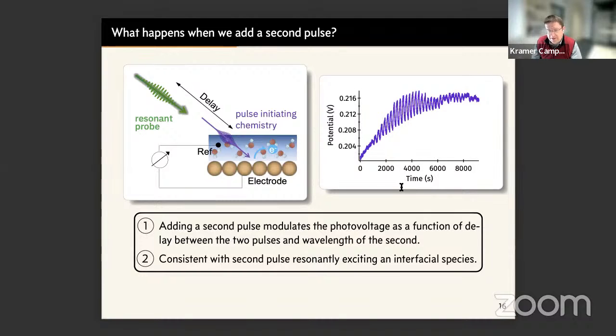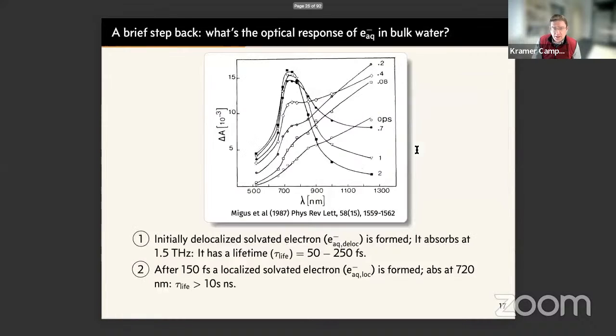So once again, this is just the seconds right off the potentiostat. And each of these spikes correspond to a different delay between this UV pulse and a pulse with different photon energy. So we want to argue then that this kind of data is consistent with the second pulse resonantly exciting an interfacial species.